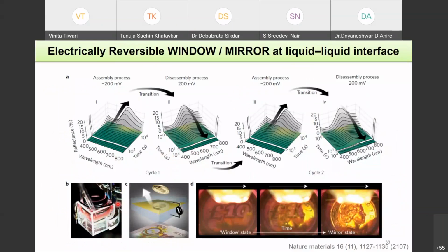So this is an experimental setup where you put a coin at the top and a banknote at the bottom. This research was done at Imperial College, and was published in Nature Materials. And there we see that this is the window state. So you're able to see the coin and the 10-pound note at the bottom, and the coin is at the top. And slowly, when you turn on the voltage, the mirror is getting formed. So you are starting to see the reflection of the coin. And this is where you see a very strong reflection of the coin because the mirror state is completely formed.